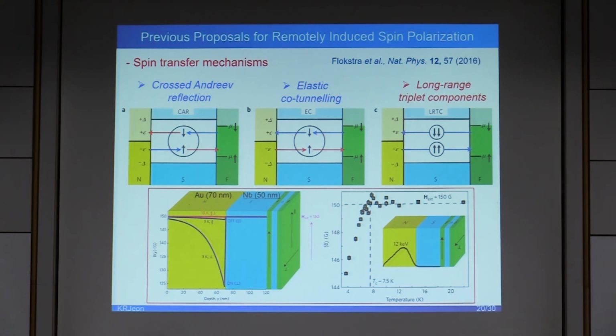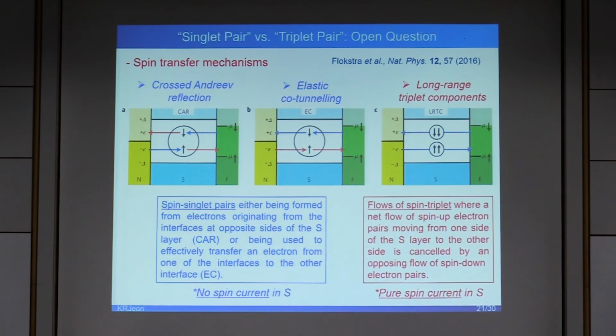The mechanisms enabling supercurrent-mediated spin transport through a singlet superconductor are crossed Andreev reflection, elastic cotunneling, or induced triplet pairing state. These three transport mechanisms were previously proposed to explain the remotely induced magnetism in a normal metal in conjunction with superconducting spin valves, in which a 70 nanometer thick gold layer is separated from the spin valve by 50 nanometer superconducting niobium layers. Of the three spin transport mechanisms, crossed Andreev reflection and elastic cotunneling via spin singlet supercurrent require the involvement of unpaired electrons within the superconducting energy gap in both the ferromagnet and the spin sink.